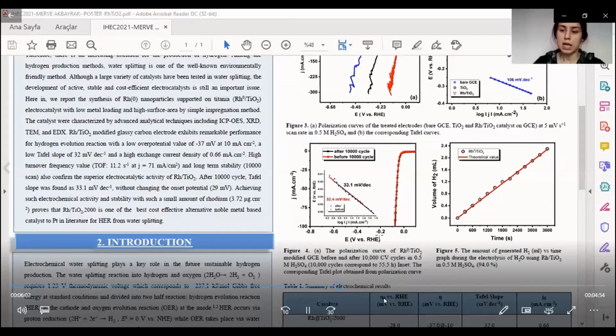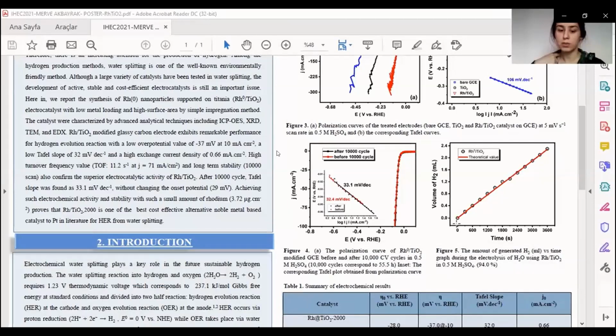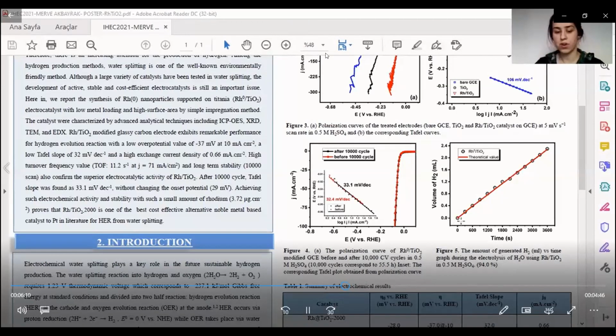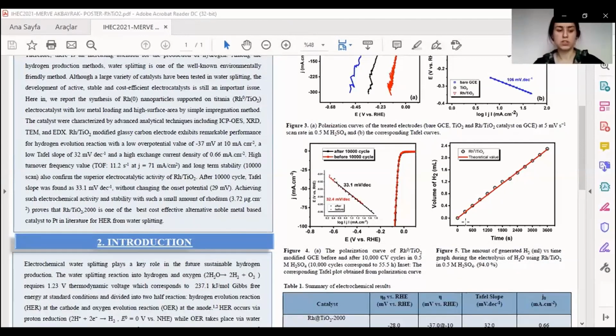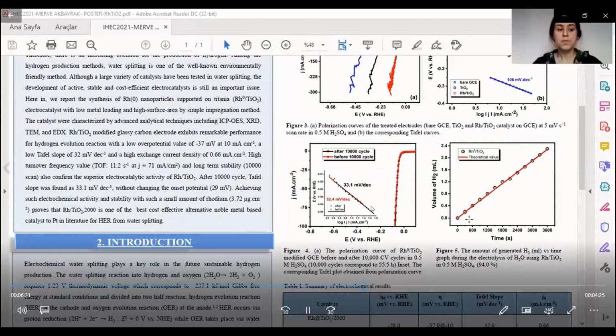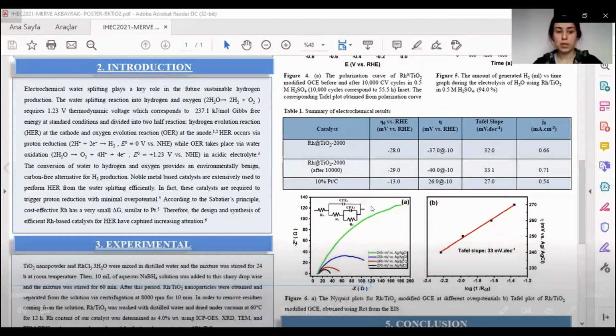The volume of the evolved hydrogen gas from the water electrolysis was measured in a Hofmann electrolysis cell and followed as a function of time. The Faradaic efficiency of rhodium titania for hydrogen evolution reaction was calculated as 94% after applying a charge of 18,000 millicoulomb. The calculated yield is also consistent with the theoretical one. Electrochemical impedance spectroscopy was also studied to determine the electrocatalytic activity of rhodium titania at different potentials. The observed semicircles at low and high frequency regions in figure 6A and B can be fitted to the inset model.